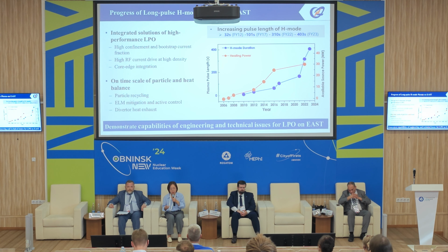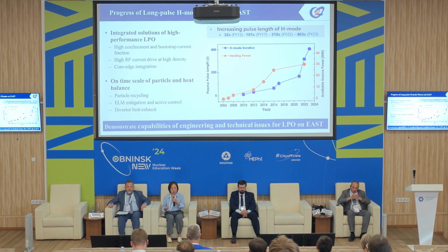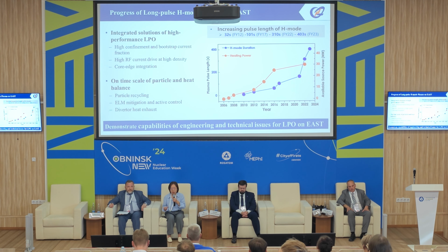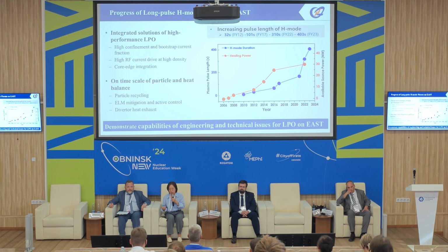Here I show you some results recently. As I said, ASIPP focuses on steady-state operation. We would like to get long-pulse operation because we use a superconducting tokamak. You can see this figure. It shows the pulse length duration extending from the beginning of the plasma until now. Actually, we got a 32 seconds H-mode plasma in 2012, and then we got a 100 seconds operation, and we got 300. Last year, we got a 400 seconds H-mode operation.